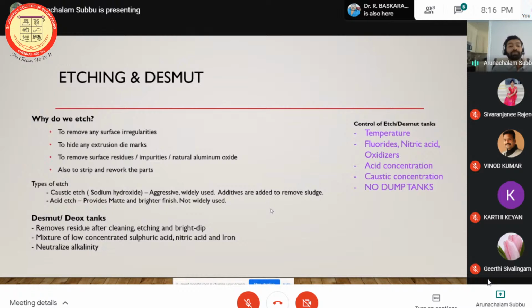And the third step is the deox or the desmut tanks, which is the step after the etching, which you do to neutralize the alkalinity. Basically, the etch is a caustic etch, so it will have a higher pH, and the pH has to be lowered, so you neutralize them in the desmut tanks. It's basically a mixture of sulfuric acid and nitric acid and iron chemistry, so it's an acid chemistry after an alkaline chemistry. You also have to maintain certain control parameters like temperature, fluorides, and the concentration of the acid or the caustic. And you don't have to dump the solution from these tanks even after 20 or 30 years, because it is a regenerating tank. It will always be operational. You just have to add some things to make sure that it's working properly.